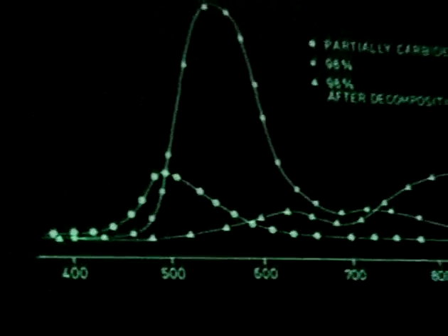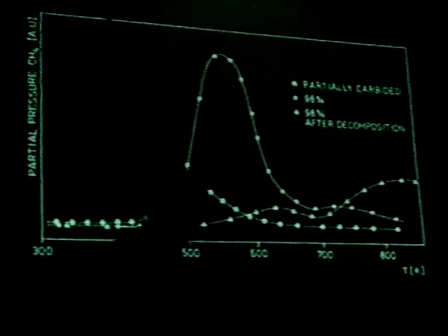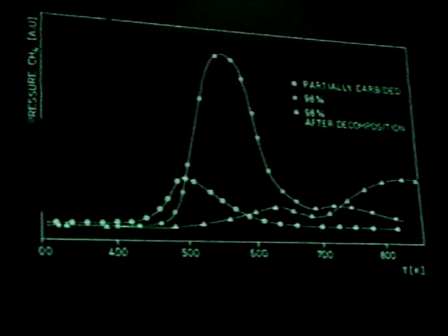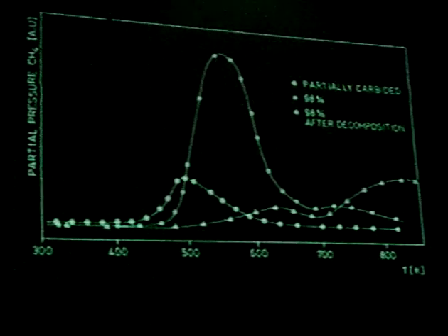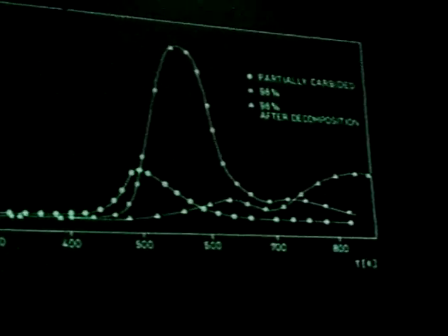Now if you are keeping the catalyst loaded by the carbon for a period of, say, 1 hour at a high temperature, you get a decomposition, and then the graphite you are having then is rather difficult to hydrogenate. So there is a decomposition of the carbide into graphite and into the metal.